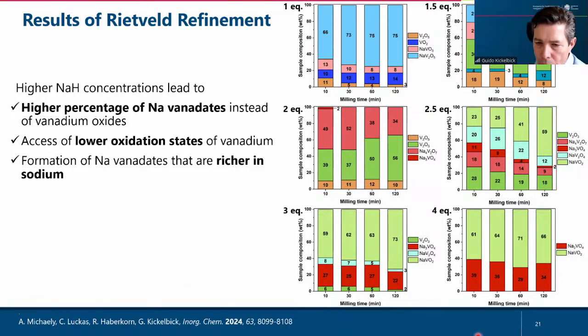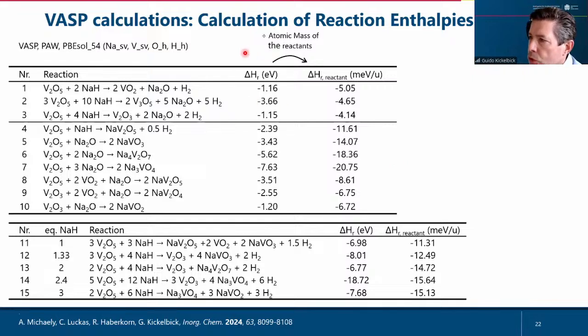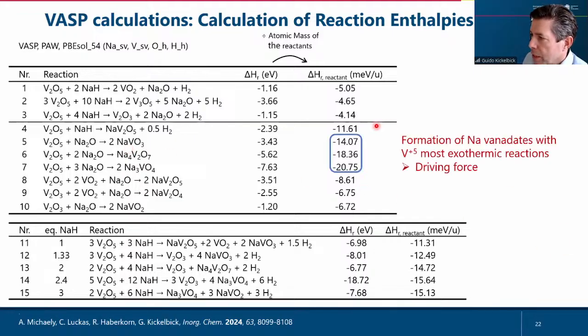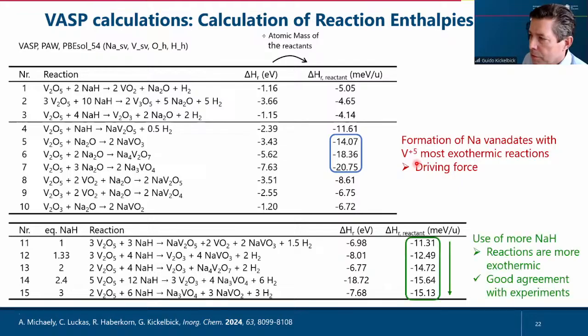The question was now, why is this reaction so exothermic? And you can follow this reaction also by calculations. So you can write on a piece of paper the probably occurring reactions with the sodium hydride, and then you do a calculation on a DFT basis. And what you figure out then is that the formation of sodium vanadates with the oxidation state 5+ is the most exothermic reaction. So this seems to be the driving force of this reaction.